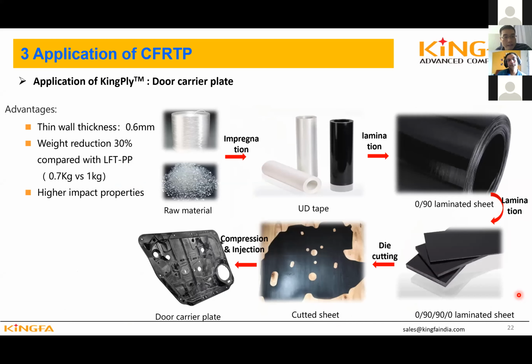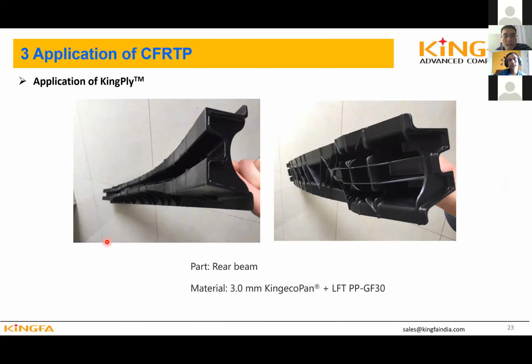And the thickness for this product is only 0.6 millimeter, and the weight reduction is 30% compared to LFTPP. And the impact property is also better than LFTPP. So with this kind of method for compression and injection together, we can make some other parts like the rear beam. We also tried using 3 millimeter KingecoPan with some LFTPP to make this part.